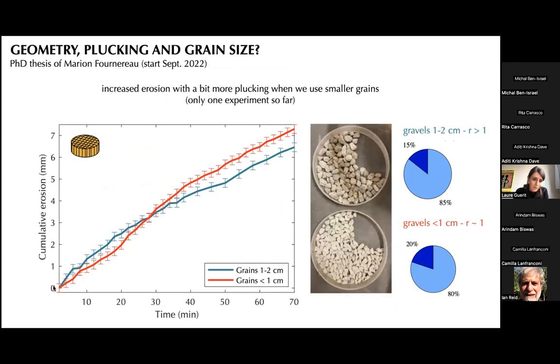So I show here the cumulative erosion through time for this experiment. In blue, it's the one performed with the grains that are 1 to 2 centimeters in size. In red, it's with the smaller grain, and we do observe more erosion and also more plucking. So grain size seems indeed to play a role, but so far we only have one experiment, so it remains to be further investigated. And this will be part of the PhD of Marion, who just started a few months ago. And in addition to this lab work, Marion will study a natural system.